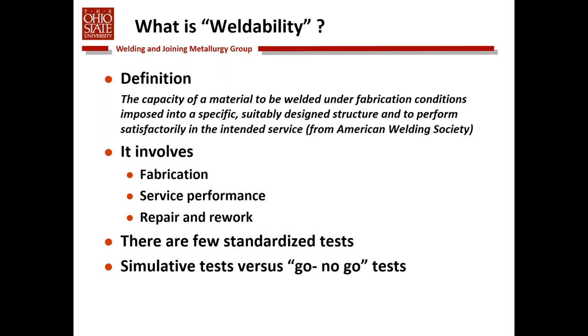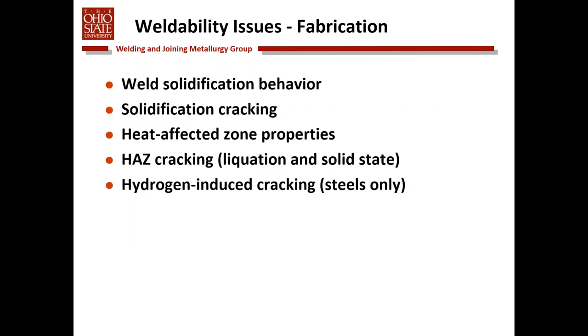There are two basic types of weldability tests. There are those that are simulative in that they try to simulate some aspect or the thermomechanical response of welded joints, or tests that are called go or no-go, which means you run a test and the sample either cracks or it doesn't crack, and that is basically indicative of the weldability of the material. And again, I'll come back to these points a little bit. Most of the tests that I'm going to talk about today are simulative in nature in that they normally involve some laboratory equipment that applies a stress or a strain to the material in order to force a material to crack under certain imposed conditions.